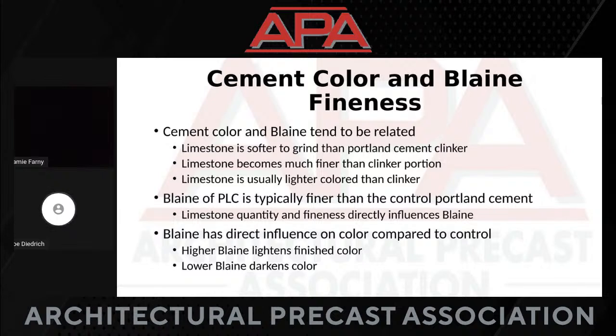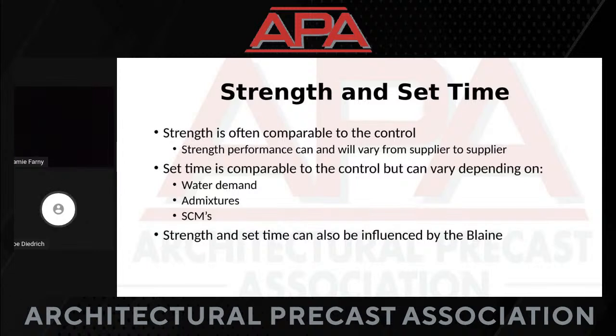The blend compared to the control, what I'm saying there is PLC blend versus the control, my type 1 versus a type 1L. Typically, you're going to see very similar, a slight increase. As Jamie mentioned, it could increase maybe 1,000 points. Every cement plant and every product the cement producer is moving, what you want to do is pay attention. Look at your current cement that you're using today. If you do change over to a PLC or try it, look at the blend. It will have a direct influence on what you're trying to do. The higher blend does impact the finished color of the concrete, and the lower blends do affect finish color. It will actually darken it.